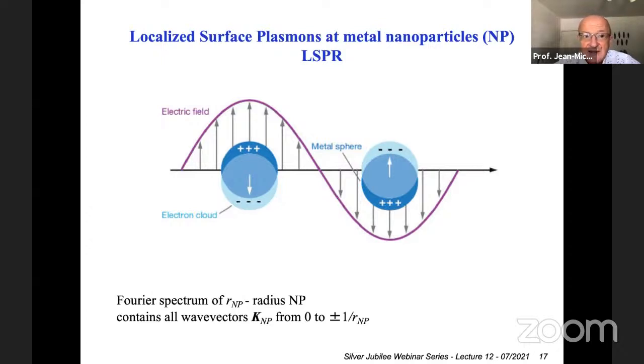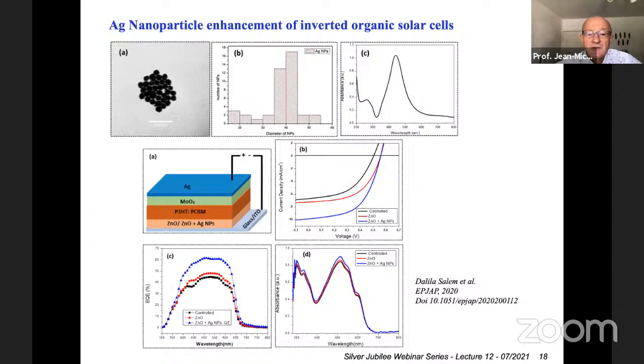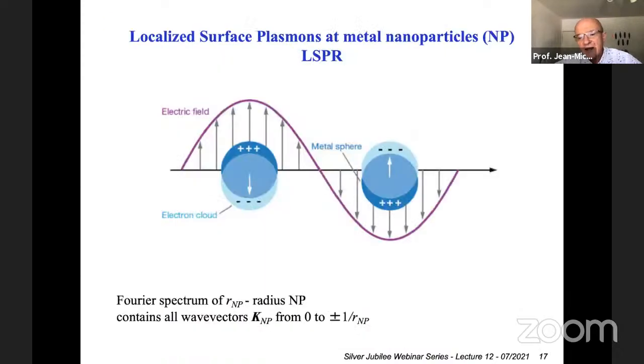But the thing is that we excite localized surface plasmons. Localized surface plasmons at a metallic nanoparticle resonate when the dielectric constant of the metal is equal to minus twice the dielectric constant of the dielectric that is around, which technically corresponds to the visible, close to the UV as well. We can use this nanoparticle enhancement for different purposes. I can continue a little bit on this one.